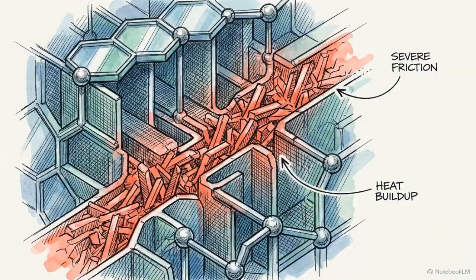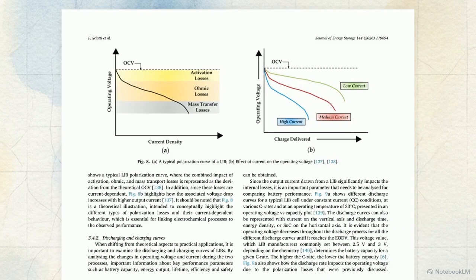The speed at which you can extract energy from the battery is strictly limited by the internal resistance of the materials themselves. This graph is a polarization curve. It is the primary diagnostic map for a cell's kinetic limitations, illustrating exactly how the battery's operating voltage drops below its theoretical open circuit voltage the moment a load is applied. The first barrier is shown in yellow. These activation losses represent the initial energy penalty required just to start the electrochemical reaction, forcing the lithium ions over the energy barrier at the electrode-electrolyte interface.